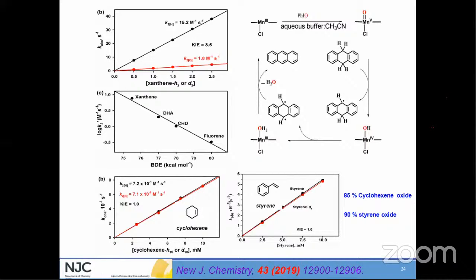To test whether epoxidation is giving quantitative yields or not, we tested styrene as the substrate. Again, styrene also gave a KIE value very close to 1, and you can see we almost got quantitative yields, right? So that is what we got when we used cyclohexene and styrene as the substrates.